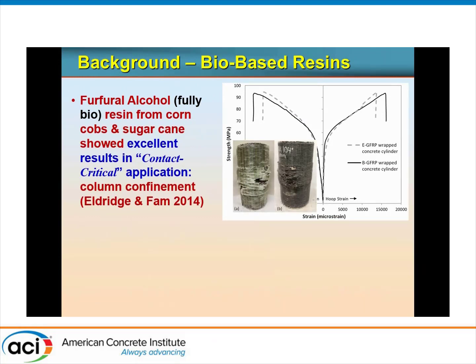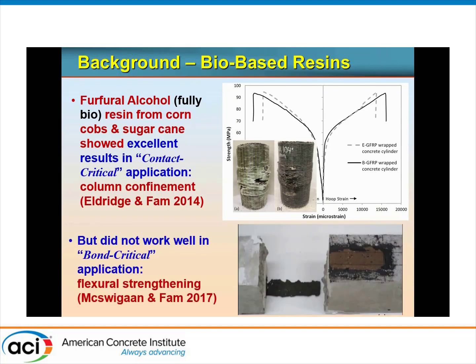So, in some of the previous work we did on this, we experimented with a type of bioresin which is, to our knowledge, fully bio: furfuryl alcohol, which is extracted from corn cobs and sugar cane. It showed excellent results, in fact, when used for confining concrete cylinders, in terms of the confined strengths, very similar to epoxy-based resins. But please note, this was a contact critical application. When we attempted to use the very same resin in a bond critical application, it was a disappointment. It did not actually bond well to concrete, and it could have something to do with the alkalinity of the concrete surface. Again, that requires further investigation.